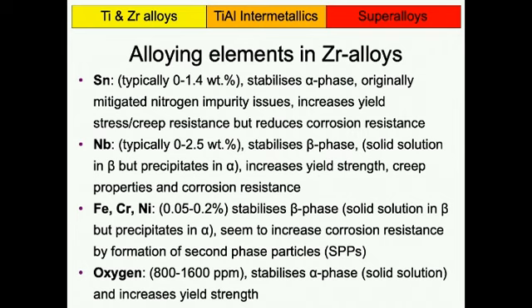Now, iron, chromium, nickel is again... These are beta stabilizers. These are these kind of eutectoid beta stabilizers. They certainly, and probably a copy and paste error which I made here, have hardly any solubility in the alpha phase. They really come out all the time. So they really form precipitates in zirconium, SPPs, second phase particles. For some reason, the zirconium community doesn't call it just precipitate, they always call it SPP. So if you read a zirconium paper, you might come across the word SPP. What they mean is just precipitates.